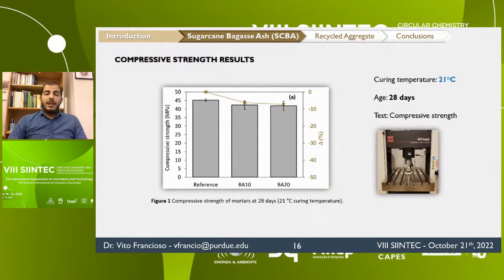Results show that the replacement of cement with sugarcane bagasse ash at standard curing temperature, so at 21 degrees Celsius, had a slightly negative effect on the compressive strength. Nevertheless, the difference compared to the reference mortar cured at the same temperature was lower than 8% in both cases, in both replacements, 10 and 20%.